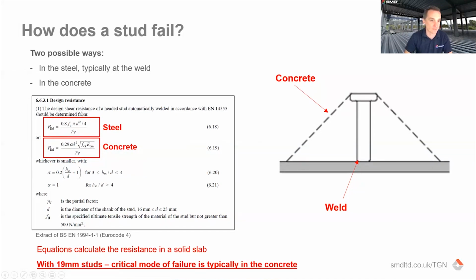So by carrying out these two equations, whichever is the smaller will give you the resistance of that shear stud in that slab for those particular criteria, depending on the size of stud you're using, etc. What I would say is, and you'll see from some photos later, with 19mm diameter studs in the form of construction we're talking about, it is nearly always, and I think almost always, the failure is in the concrete, not in the connection between the stud and the beam. And you can kind of deduce maybe why that is as we go through.